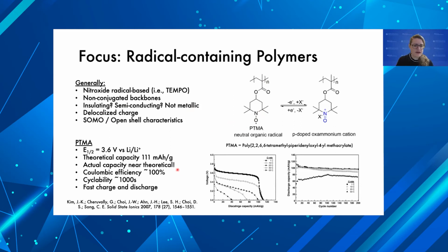As far as the polymer goes, this polymer has a half-wave redox potential of 3.6 volts versus lithium, which is quite high, a theoretical capacity of 111 milliamp hours per gram, which you can easily achieve in cycling, high coulombic efficiency, and very high cyclability. And you can get fast charge and discharge. In this graph, you can see that you can get C rates up to 50 C. In other words, that means you can charge and discharge your battery in a minute if you like, or if you do a rate of 1 C, in an hour if you like, depends on what you're going for. So you can get very high powers.